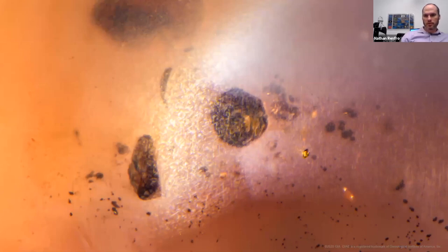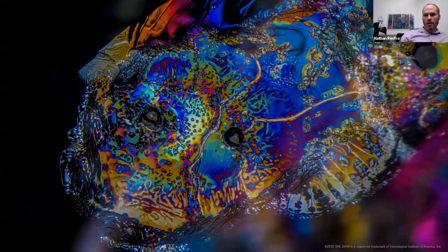There are some other dark inclusions in there, probably metal sulfides — these are common inclusions in secondary Montana sapphires. There are also negative crystals at the very core, probably filled with a glassy melt in most cases. These are what we call decrepitation halos, where the core negative crystal has ruptured and the contents have spilled out into a fracture parallel to the basal plane. Over time that fracture is partly re-healed, giving a netted appearance — the dark areas are where the sapphire has healed, and the colorful areas, using an oblique fiber optic source, show thin film interference colors. These kinds of features are pretty common in secondary Montana sapphires.